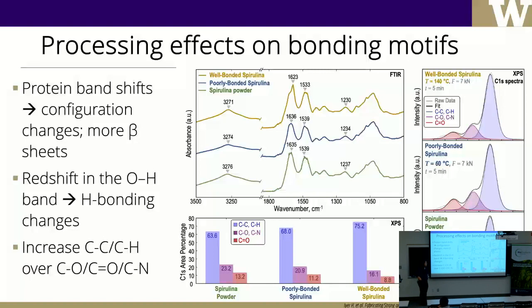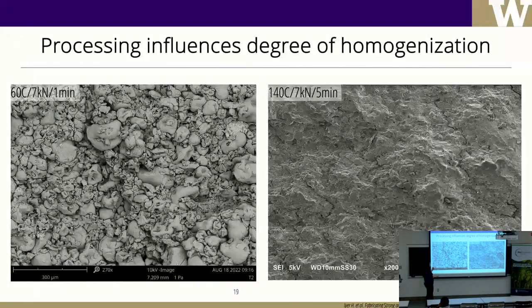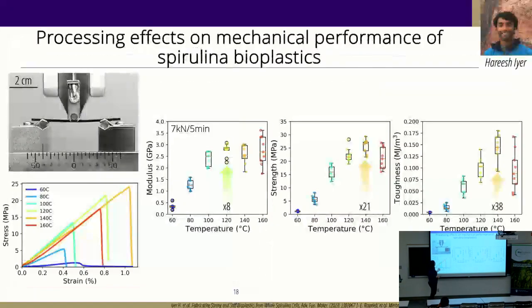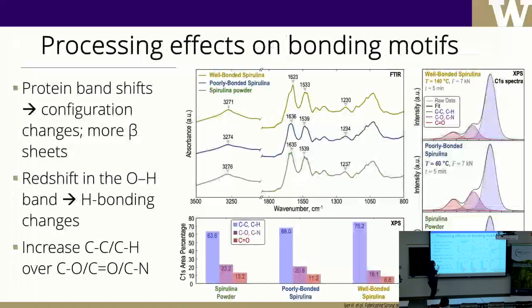Then we will go in with spectroscopic methods, so with FTIR and XPS, to start understanding what is happening to the bonding in the polymers that we have. So here we have the FTIR. The green is going to be our powder as it comes out of the pond, no treatment. And the blue and the yellow are going to be the poorly bonded sample that we saw before. So the blue corresponds to this condition, and the yellow corresponds to the well-bonded sample.